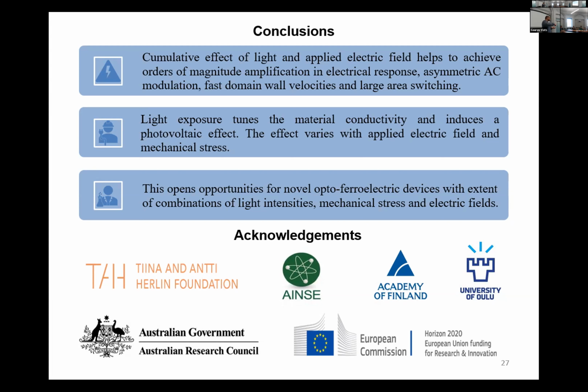Then you are collecting more charge because of increasing surface area. So one should be very careful. Even with the higher stress, if there is a little bit of pinching, the surface area is increased. Also, did you check how much time it takes to get back to its original state after mechanical poling? It's immediate, within the next scan. Optical poling takes a bit of time, but mechanical goes very fast.